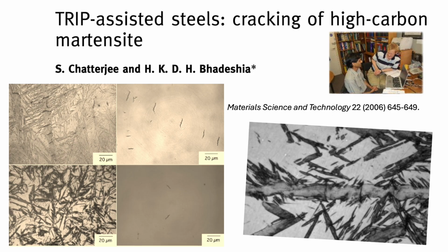Less tolerant of plastic relaxation, you mean? Exactly. Plastic relaxation is just the material yielding a bit, deforming locally to ease the stress. Think of mild steel, it bends before it breaks. It's ductile. But these hard martensitic steels, they're brittle, they don't have much give, so when stress builds up during that violent quench, instead of relaxing by bending slightly, they just crack. Catastrophically sometimes. That makes sense. Less give means more prone to breaking under stress. What's the first type of stress?